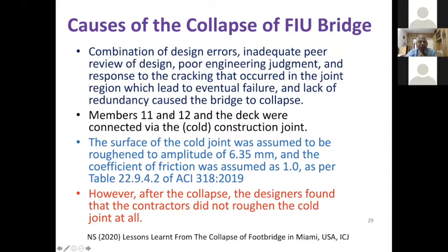Actually, there was a truss. So from the previous photo, it may not be clear, but there was a truss. And members 11 and 12 and the deck were connected via a cold construction joint. The surface of the cold joint was assumed to be roughened to an amplitude of 6.35 millimeters, and the coefficient of friction was assumed as per ACI 318-2019 as 1. But after the collapse, the designers found that the contractor did not roughen the cold joint at all.